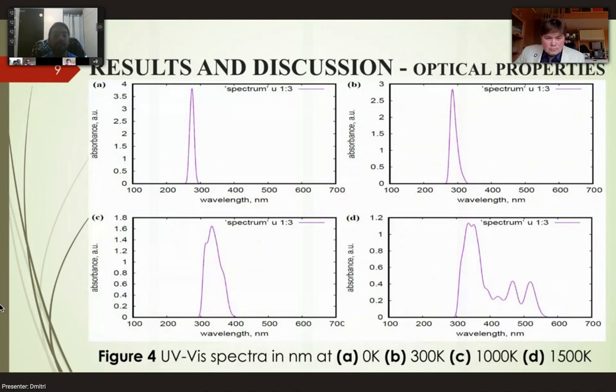Also, you see the optical property, and it's shifting from left to right. So it's going flatter from left to right. And you see at the higher temperature, at 1500 K, there comes an extra lobe, with lower amplitude, which is a clear indication of the ionic movement and the broken bonds for our model as we increase the temperature. Next, please.